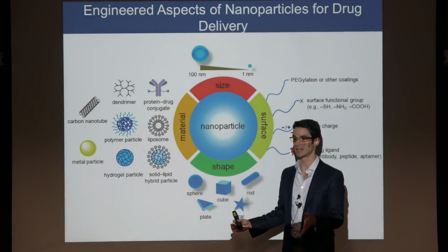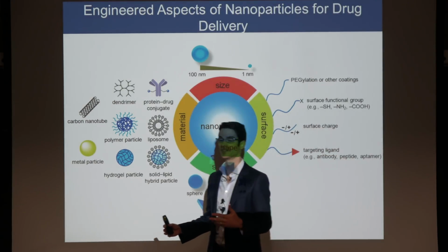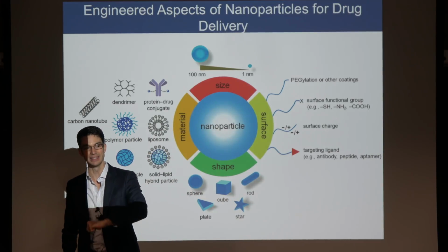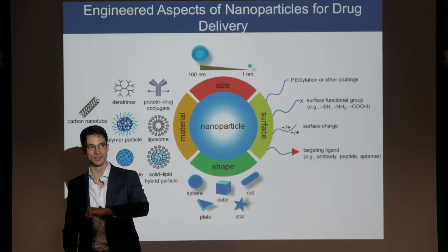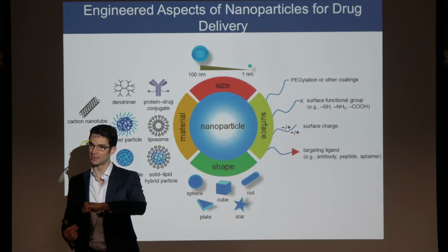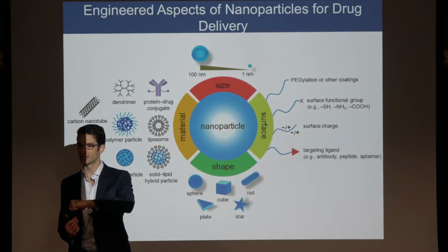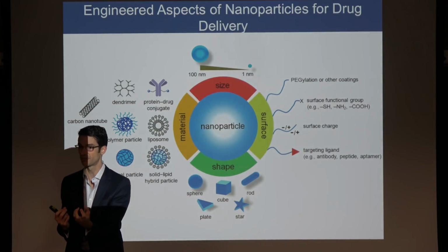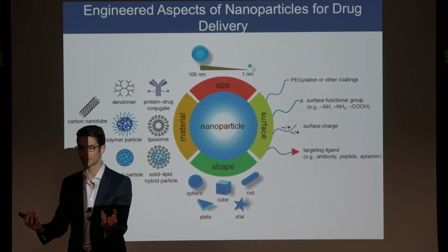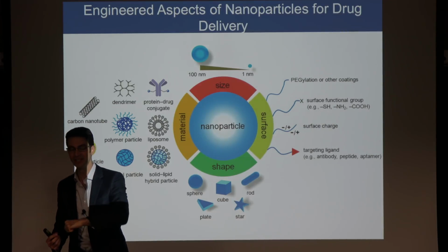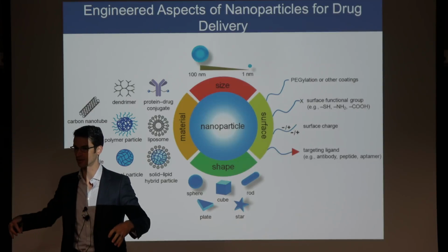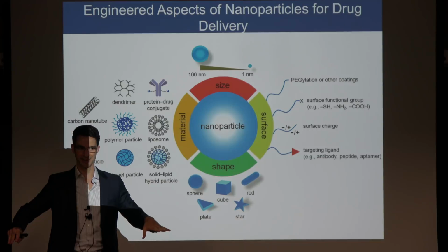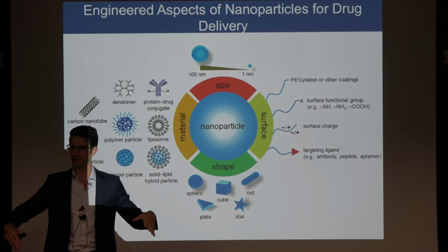templates. That's the technique that I mentioned in our discussion of unconventional nanofabrication, where you take a fluoroelastomer and you print it into a precursor, and because you have a low surface energy Teflon-like surface, you exclude all of the stuff from between the recesses in the mold, so you have isolated nanoparticles instead of nanoparticles that are connected everywhere by a thin scum layer. Literally called the scum layer or the flash layer.